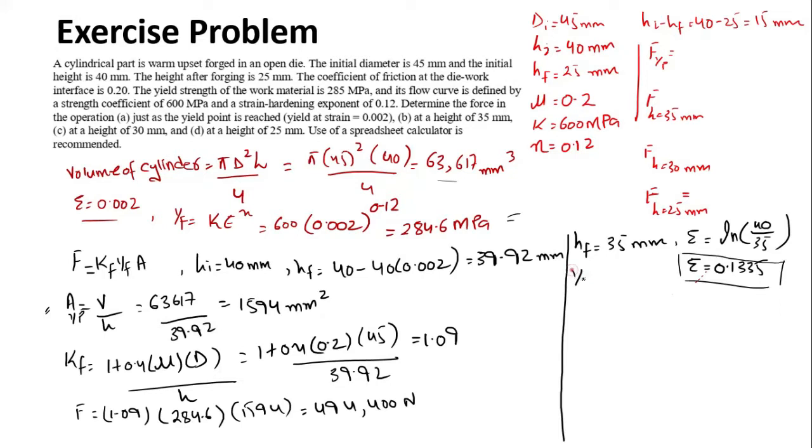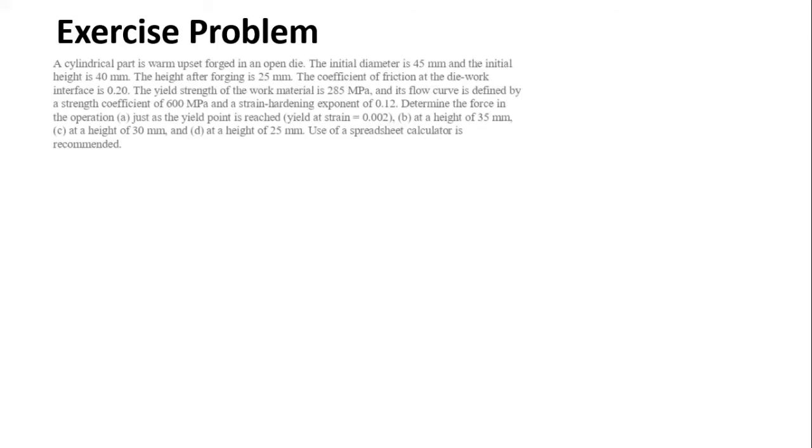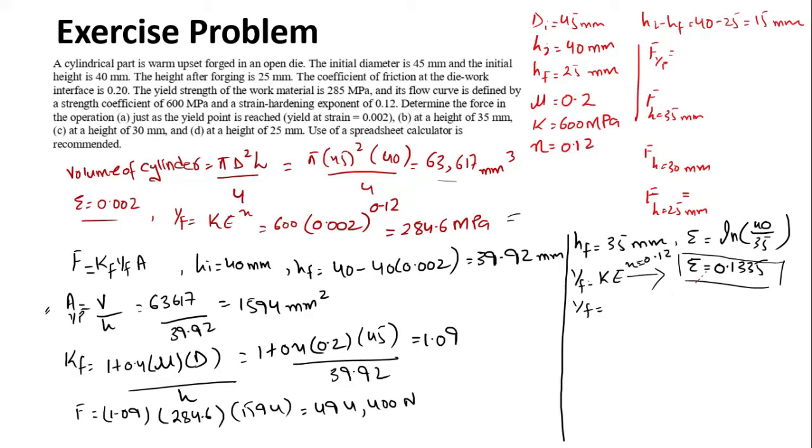So based on this strain, you can find out the flow stress, that is K strain exponent n, the strain hardening exponent. We have the value of K equal to 600 megapascal, and the strain is this one, and the strain hardening exponent is 0.12. We can simply put these values in and get the answer, and that would be equal to 471.2. This is the value of the flow stress.